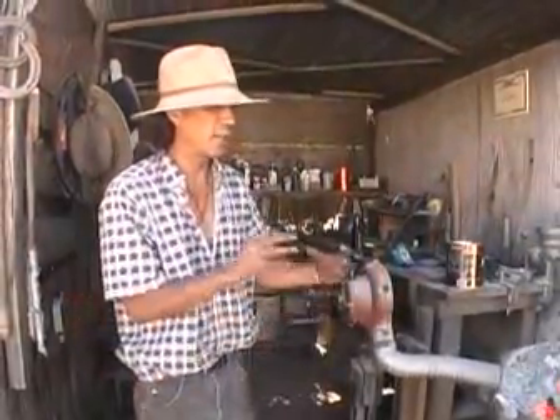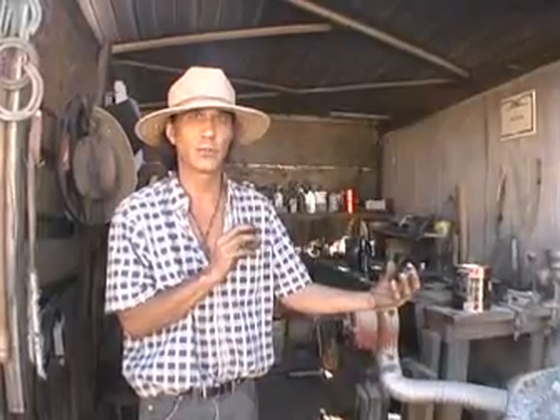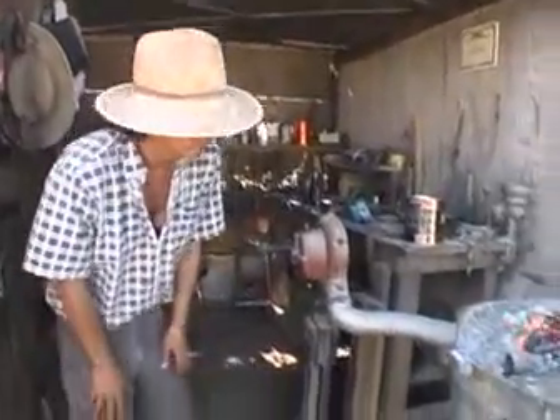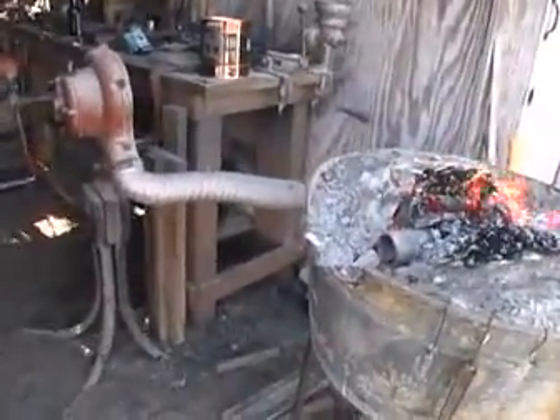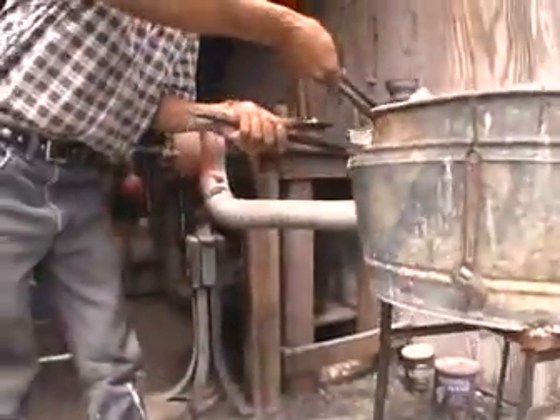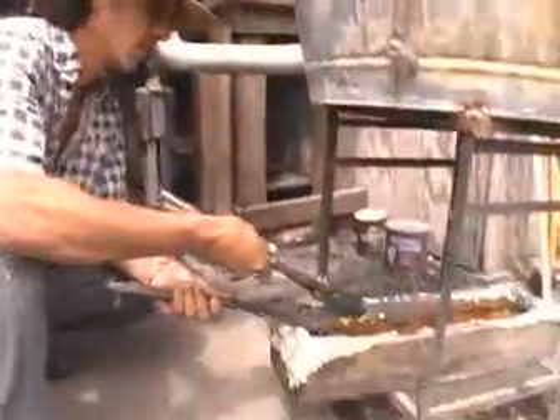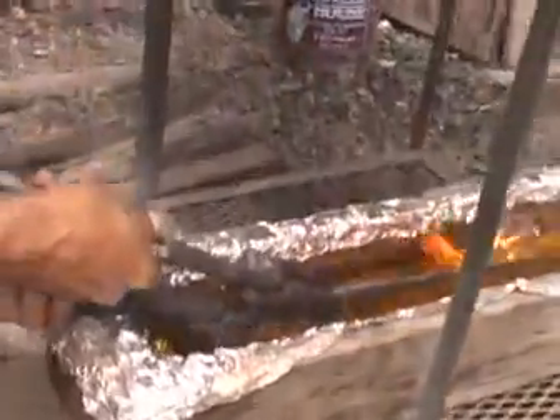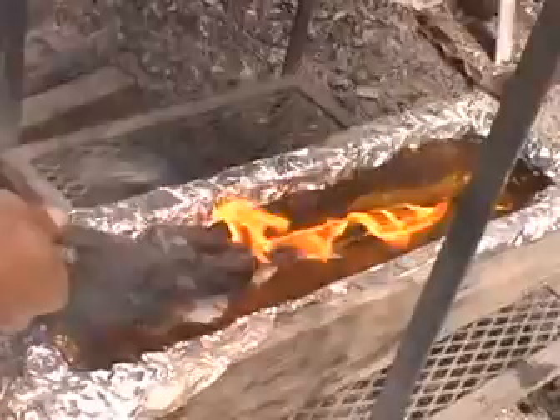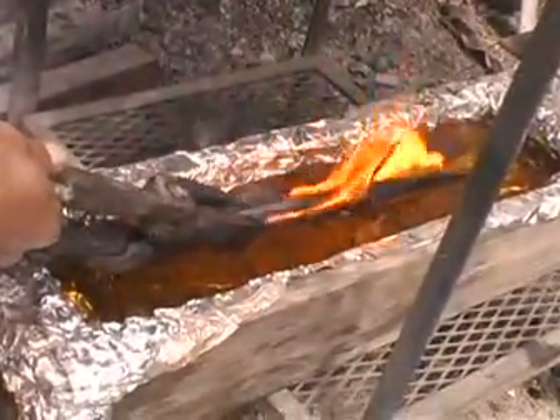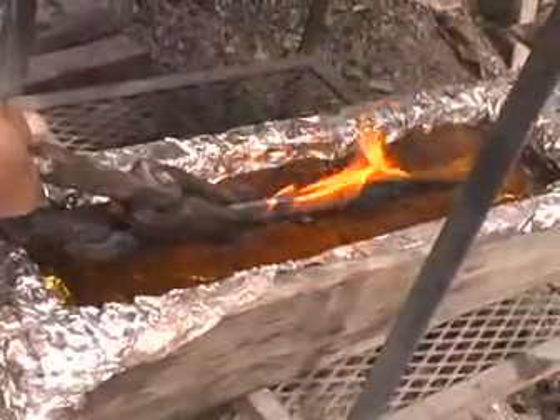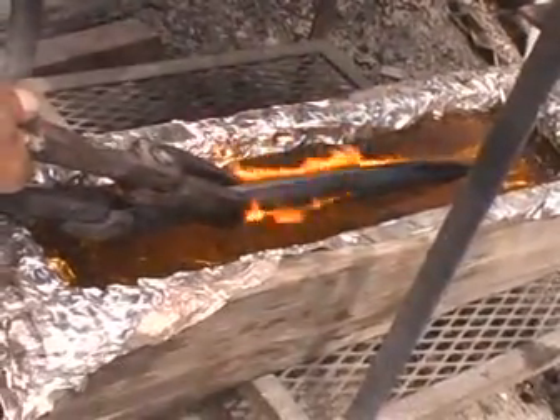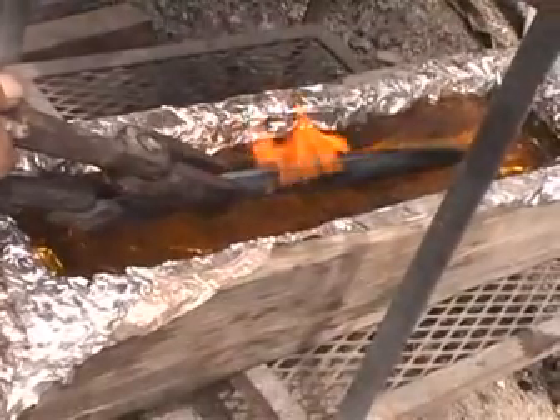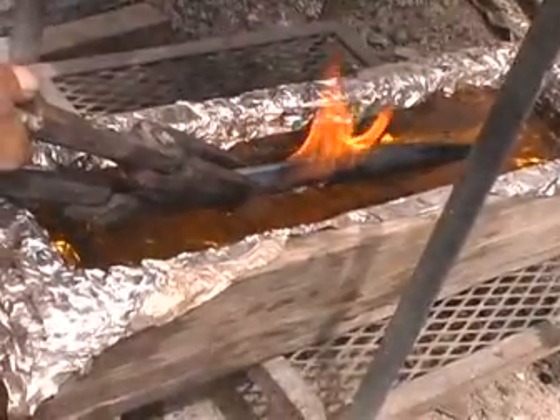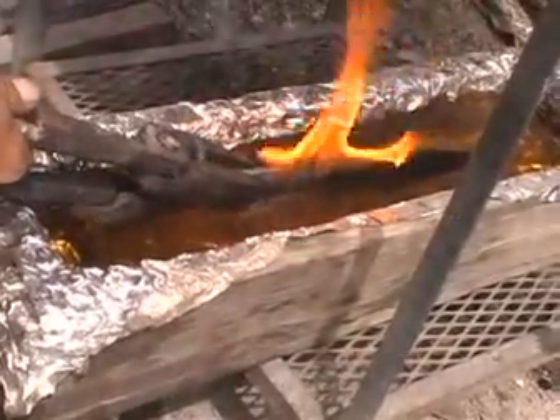I just leave it in until it reaches the temperature that I want, which is just a cherry red, and maybe 1 minute longer, and then it goes into the oil, which is just about now. So if you're ready, first I go in deep. And then I lift it back out just a little bit so the remaining heat in the back can spring temper the middle section of the blade. This is vegetable oil. Then I just go in and out a little bit.